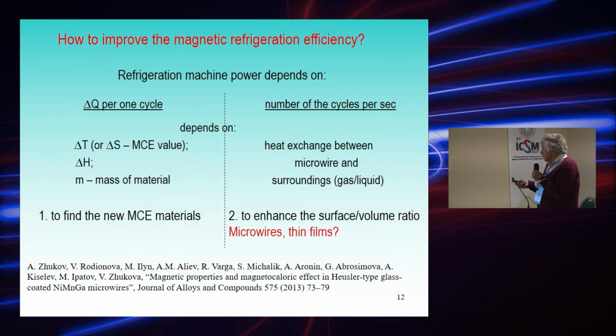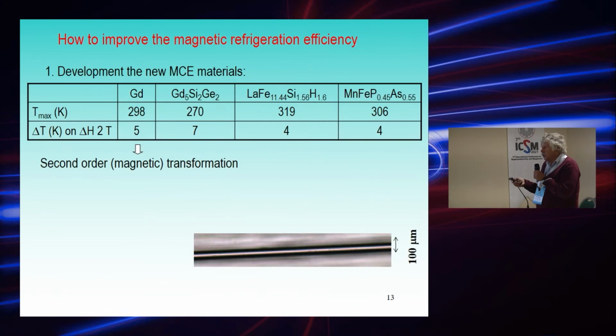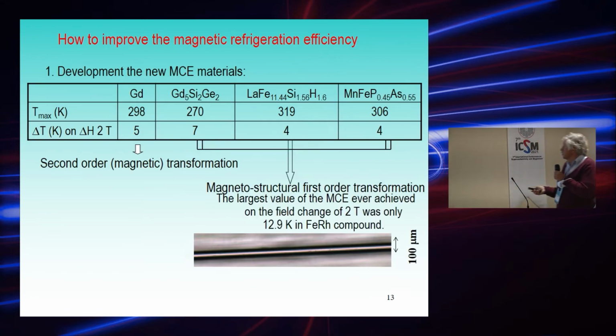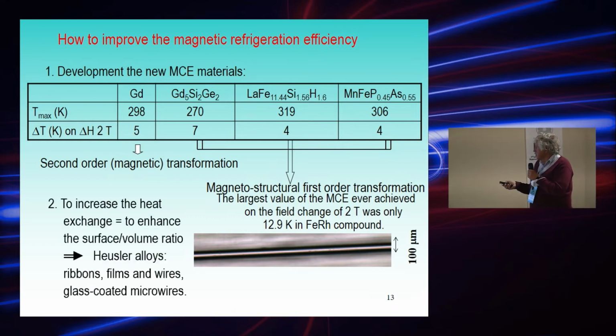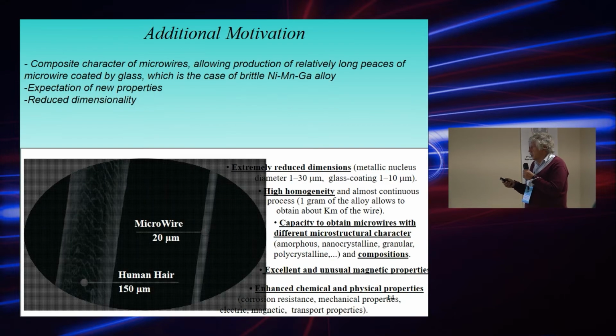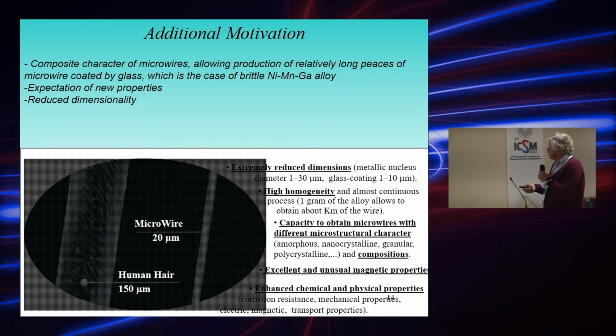One of the possibilities is to use microwires, because thin films of these materials are quite tricky to prepare. We are trying to prepare microwires and to look for compositions where we can get magnetocaloric effect and related properties suitable for applications. An additional motivation is that our materials are about one order thinner than human hair, and from 1 gram of material we can prepare about 1 kilometer of microwires.